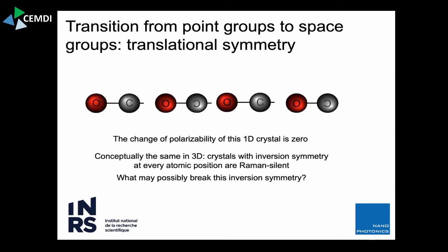The problem is, I didn't do anything. If this one has the two oxygen inbound, this one has the two oxygen outbound. So the translational symmetry means that if you just double the unit cell, you have, again, a symmetric situation through the translational symmetry of the crystal. That means the overall polarizability of your crystal does not change. So this mode is active in a molecule, but inactive in a crystal, because overall the translational symmetry means the total polarizability of the sample doesn't change. Now, you can extend this easily to three dimensions. And now the question we can ask ourselves: how can we possibly break this inversion symmetry?